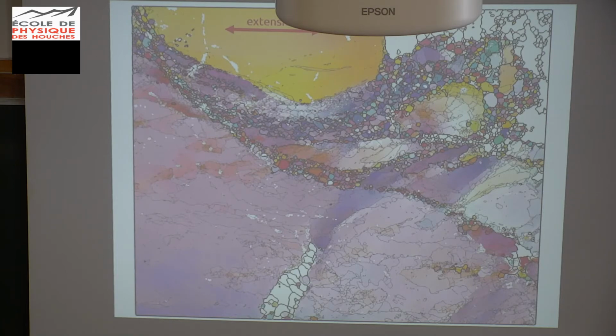You can see in the subgrains that a lot of subgrain cells are formed, and that sometimes these subgrain cells turn into real dynamically recrystallized grains, and the size of these subgrain cells is about the same as the dynamic recrystallization grains, an average of 10 microns. So overall, all these factors indicate that the dynamic recrystallization mechanism that operates is subgrain rotation. This is what we are going to study.